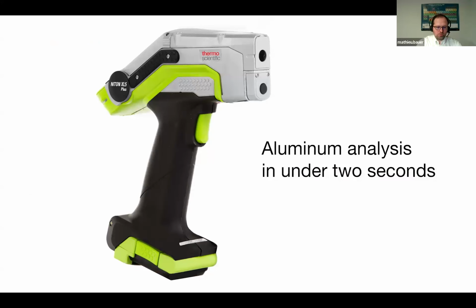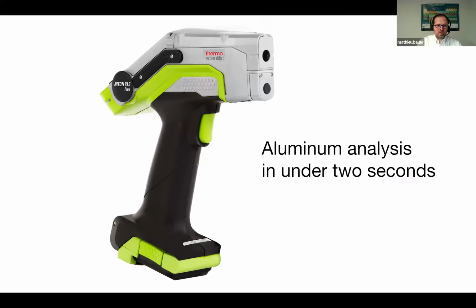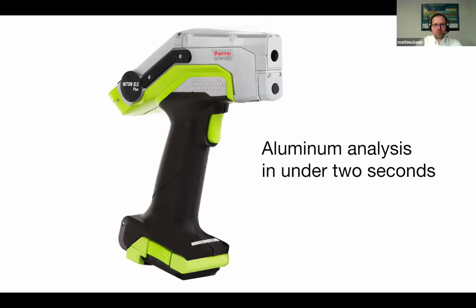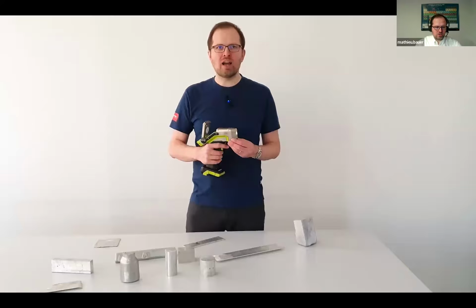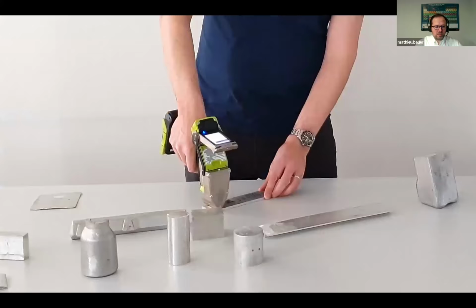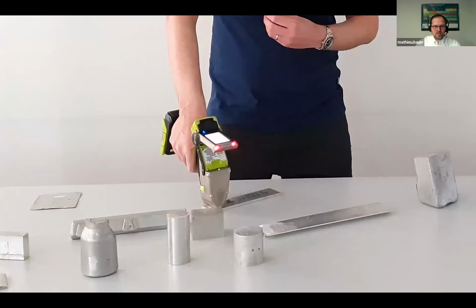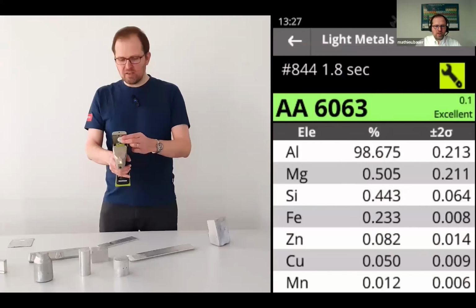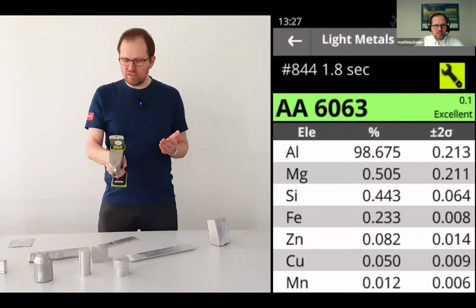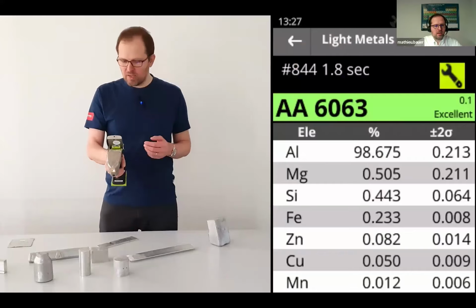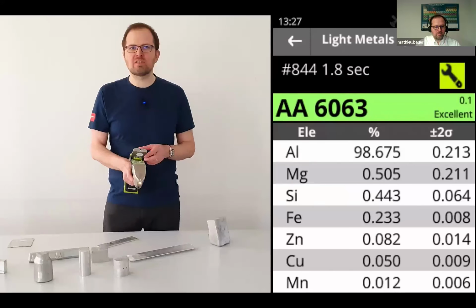So here is a short video to demonstrate how fast the identification of aluminum alloy can be done. And as you can see here, we identify within less than 2 seconds a grade of 6063 containing only 0.5% magnesium and about 0.5% silicon.